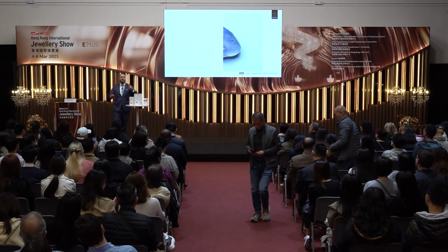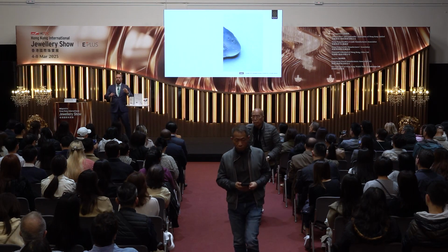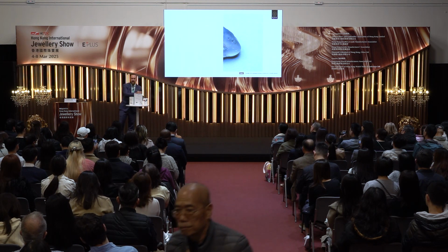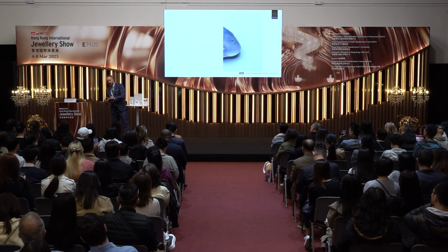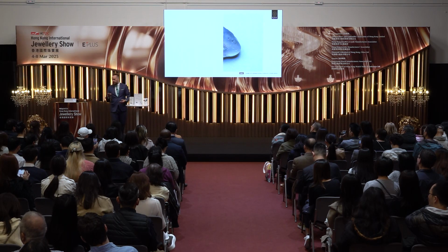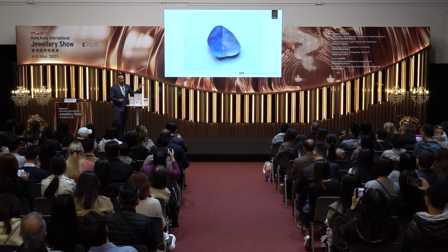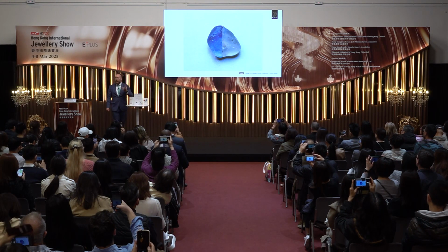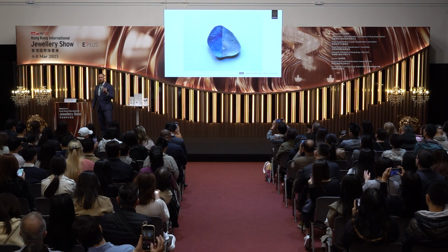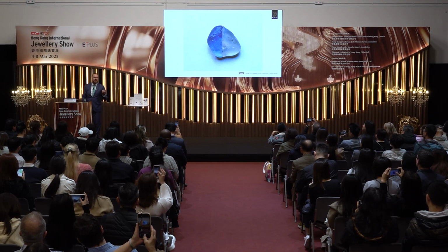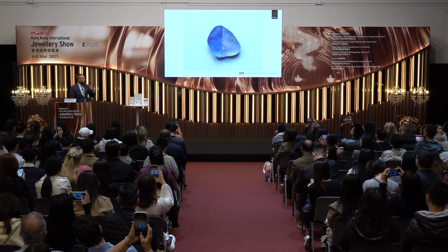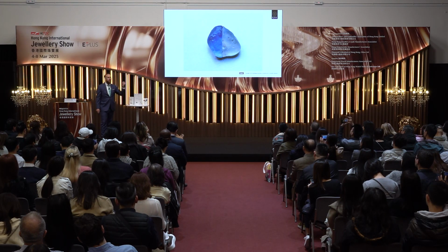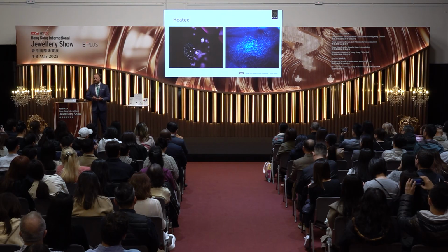So with corundum, there's 2 challenges that we need to face. We need to deal with that clarity, so improve the cloudiness or the fractures in it, and then we want to improve the color as well. And with heat treatment, we can do both, because this is the other half of the stone, where we can see that the color has drastically improved and the cloudiness is completely gone. So we were able to turn that milky, cloudy, whitish stone into a very beautiful, transparent blue pebble. So that is the 2 main reasons why we do heat treatment on rubies and sapphire.